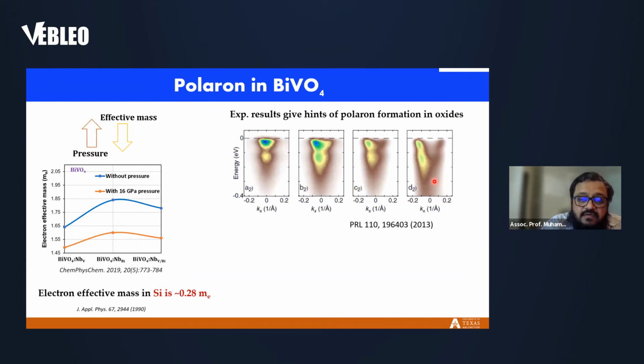This slide I will go very quickly. Just to show another property: if we calculate the electron effective mass for pristine bismuth vanadate, it is 2 times the bare electronic mass. Initially, we tried to lower the effective mass by doping with a more delocalized dopant like niobium. The effective mass goes down. However, it is still more than 1.5 times the bare electronic mass.